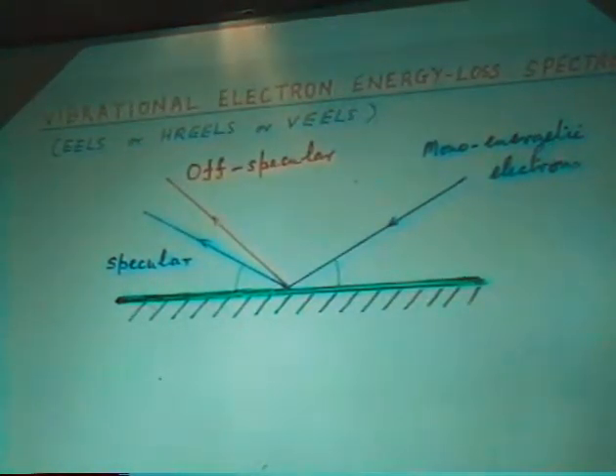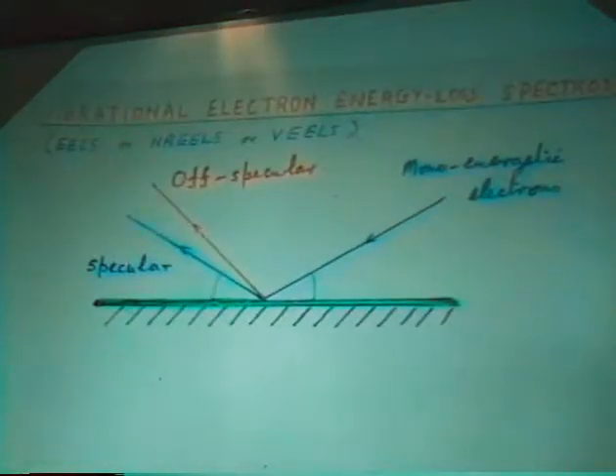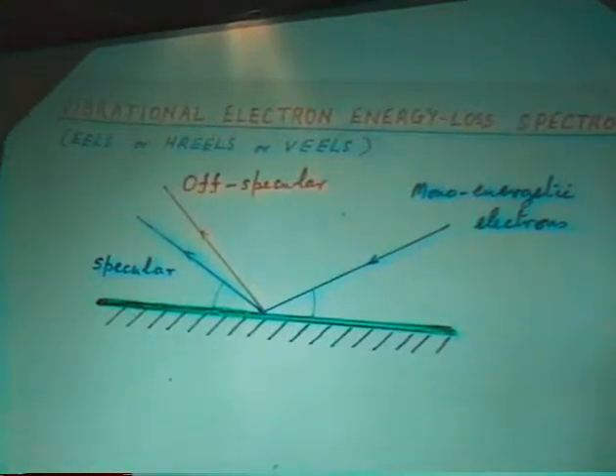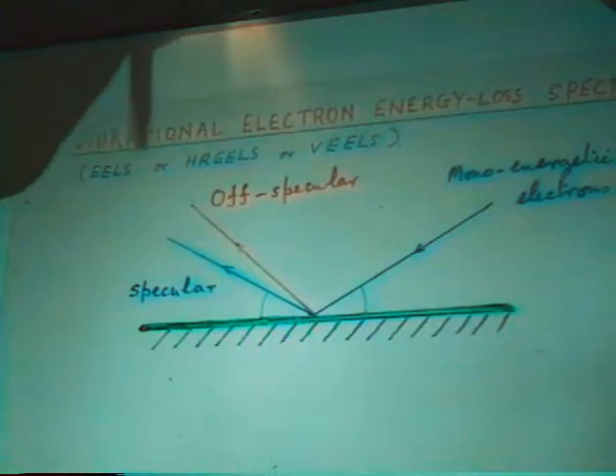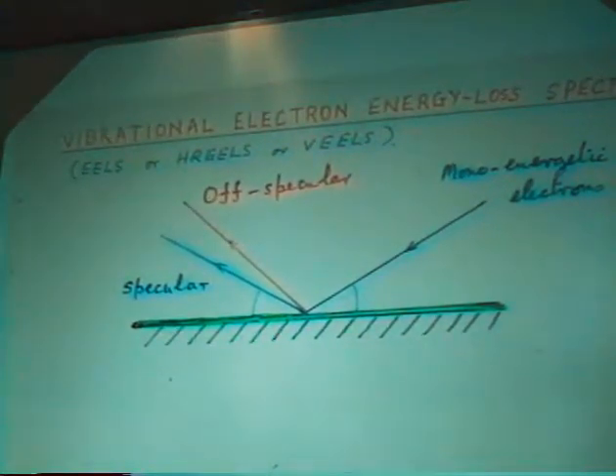If you make the measurement in the specular direction, angle of incidence equals angle of reflection, then in large measure the most potent process is dipolar, as in infrared spectroscopy, and the metal surface selection rule operates. If you go off specular, which is possible because the wavelength of electrons is more comparable to the wavelength of the atomic separations in the surfaces, you can pick up weaker features, which, however, can give you information about parallel modes as well as the perpendicular ones.